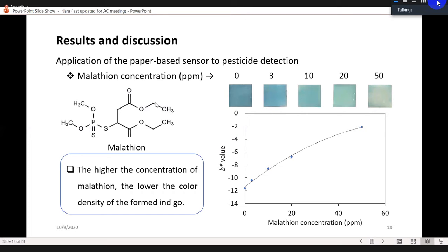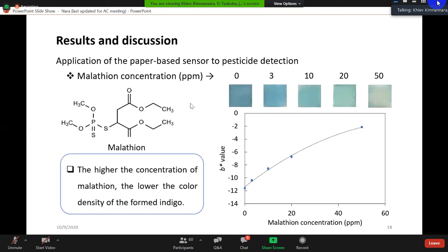Results. In my study, I applied malathion as one model pesticide, and malathion is a member of the OP pesticide group. From the result, we can see that the color density of indigo blue decreased dramatically when we increase the concentration of pesticide from low to high. In my study, I applied from 3 ppm until 50.